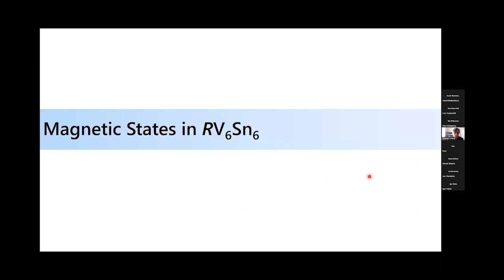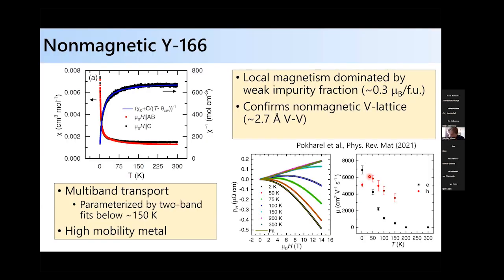Okay, so what we wanted to try and do when looking at these systems is understand to what degree we can manipulate magnetic order in these compounds. The typical game with rare earth ions is to tune the lanthanide ion judiciously. So first off, starting with non-magnetic yttrium vanadium 1-6-6. Okay, so indeed, if you look at the susceptibility of this system, it's non-magnetic. The vanadium ion doesn't carry any local moment, so it's more or less a Pauli paramagnet with some very weak upturn at low temperature due to some dilute fraction of paramagnetic impurities.